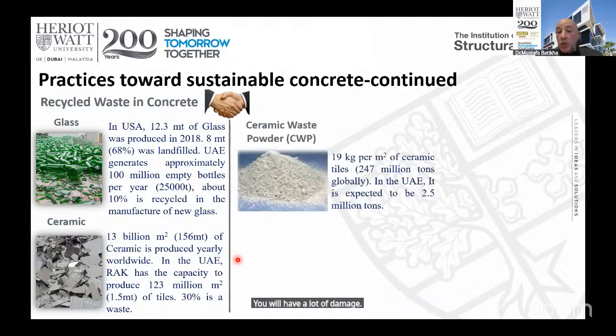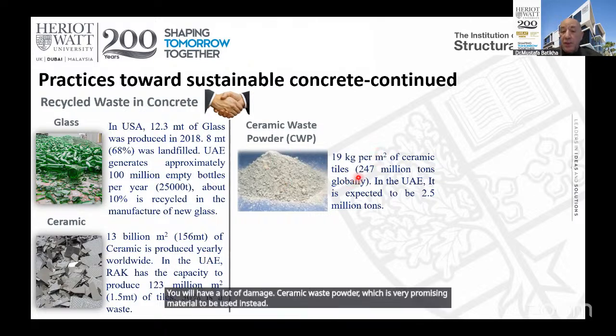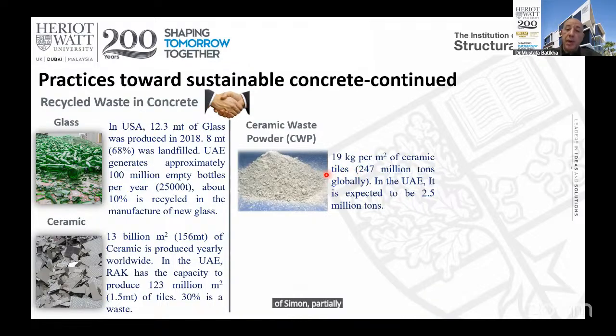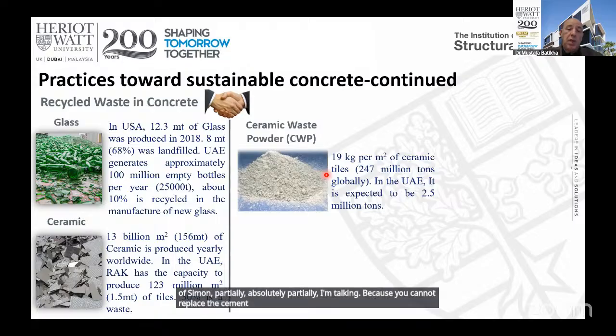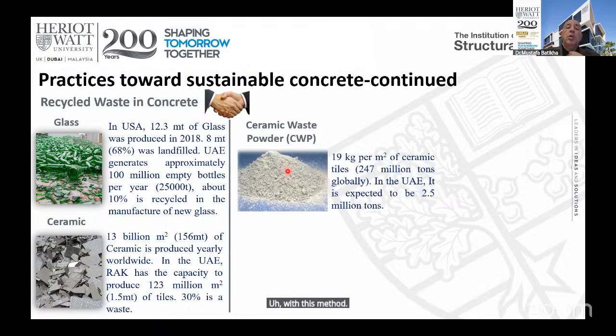Ceramic waste powder is a very promising material to be used instead of cement, partially, absolutely partially I'm talking, because you cannot replace the cement fully with this material. Do you know that each square meter of tiles produces 19 kilograms of ceramic waste powder? It is produced during the polishing process of the tile.